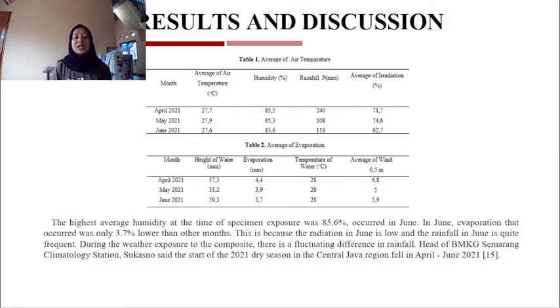And this is the result, and the results from the average of air temperature. The highest average humidity at the time of specimen exposure was 85.6%, occurring in June. The evaporation that occurred was only 3.7%, lower than other months. This is because the radiation in June is low and the rainfall in June is quite frequent.